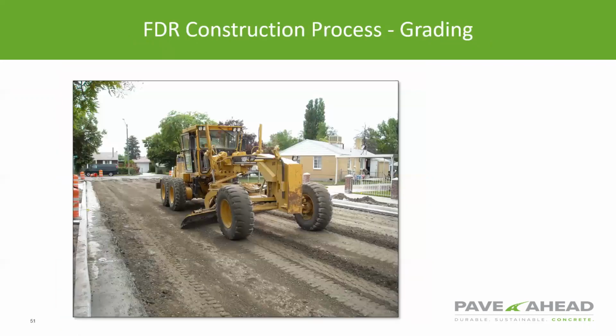And then you have your grading, where again you want everything to be graded back to its proposed elevations, cross slopes, and the grading process. As soon as the powder or the material gets blended into the ground, obviously if you're working with a slurry, you can't let it sit on the ground for 3 hours. A powder, you can let it sit on the ground for 3 hours if it's not soaking up moisture. But from once you get the mixing started to the final grading and rolling, in my opinion, it should be closer to that 2 hour mark.